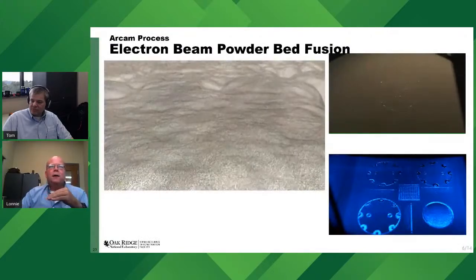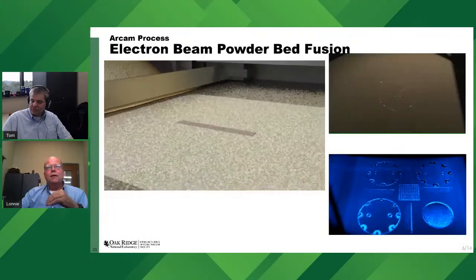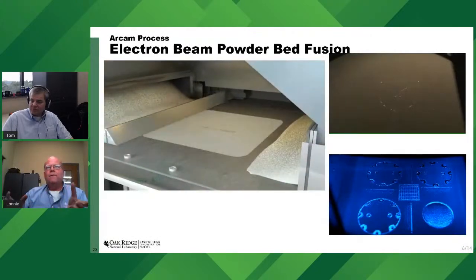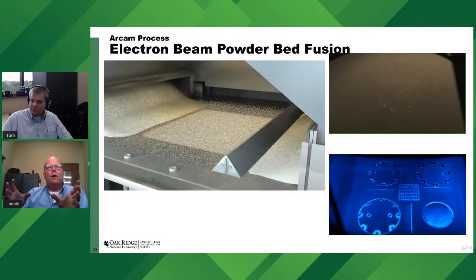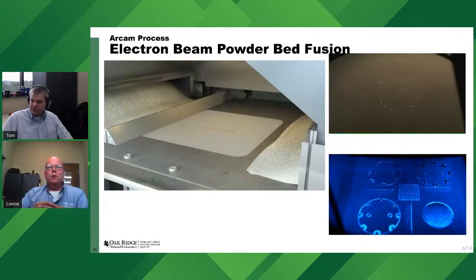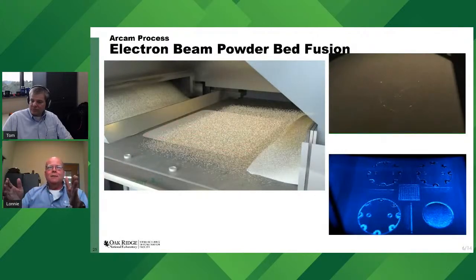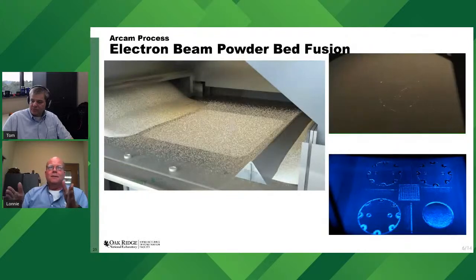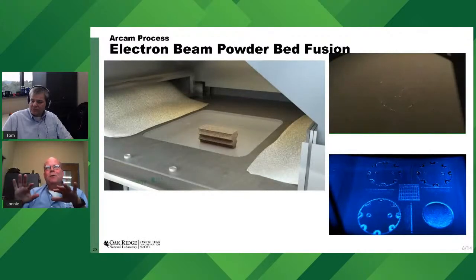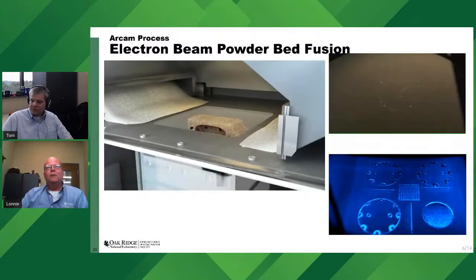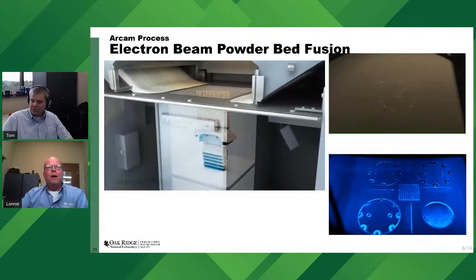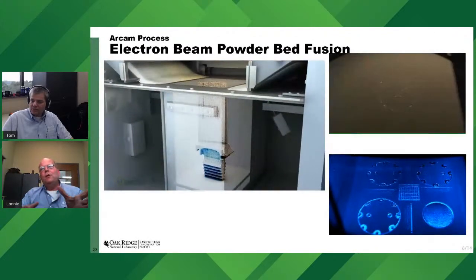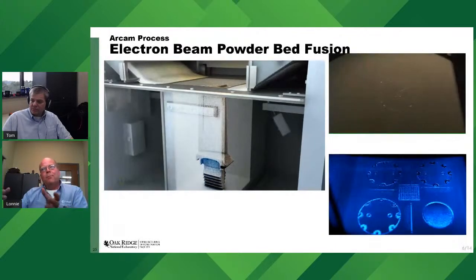So the advantage there is that your residual stresses are very low. You can make very complex features without worrying about the part warping or curling. The downside is that powder bed, when you're done, is 600 degrees C. So that machine is going to have to sit idle for a day or two to allow that powder bed to get cool enough